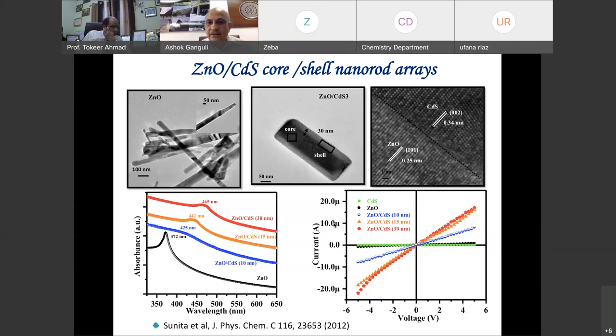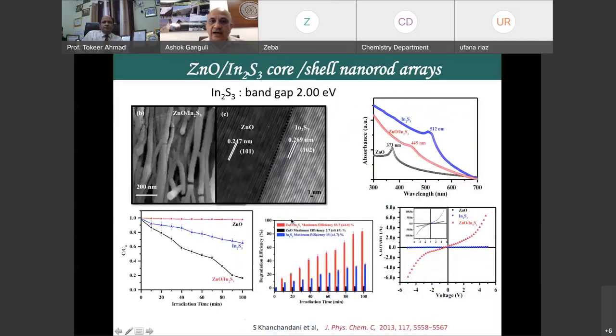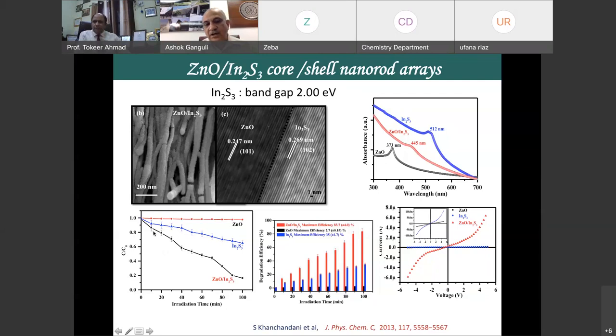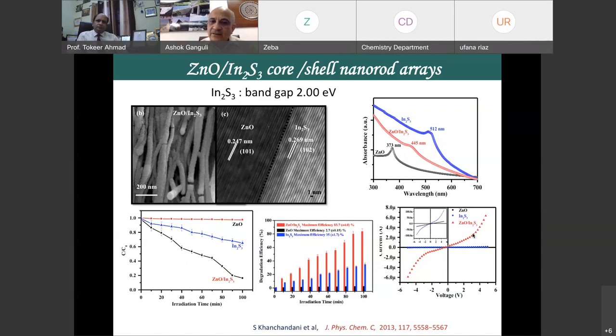We repeated the same approach using indium sulfide instead of cadmium sulfide to make core-shell structures. You can shift the absorption and get very good photo catalysis. With organic dye degradation: zinc oxide alone shows very poor degradation, indium sulfide alone is not very good, but the core-shell structure shows the concentration of the organic compound decreasing very fast. The photo current of the core-shell (red curve) is much higher — you can make very good materials with core-shell structures.